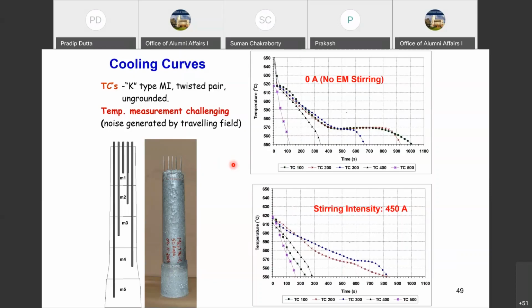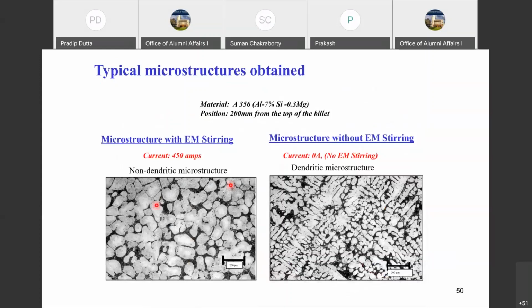And then we produce a non-dendritic microstructure when we stir with nearly about 450 amperes. And when we do the same experiment without any stirring, we find the usual dendritic microstructure. So that was our first success in producing this kind of stirrer.